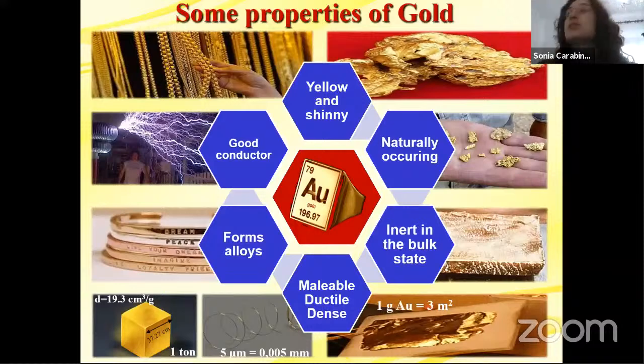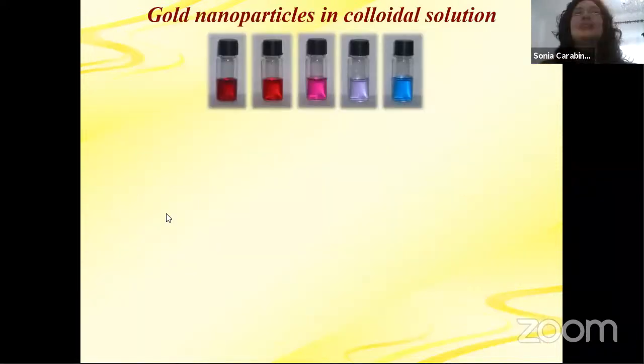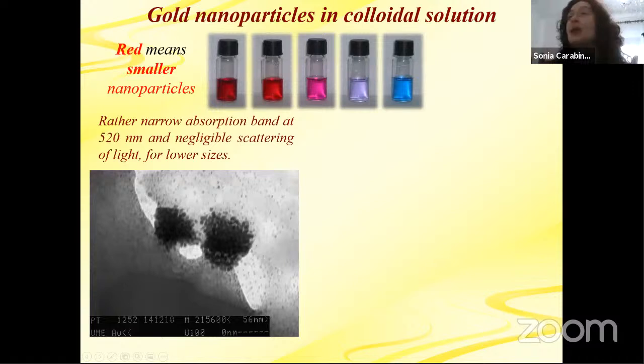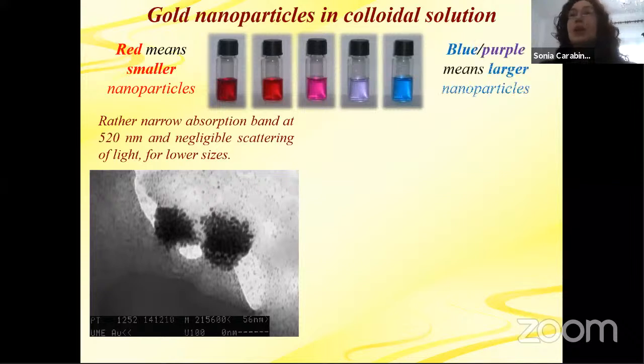Well, we have gold nanoparticles in solution. They have different colors. They are not yellow like the gold in the bulk state. So it's quite interesting, because if we have a red solution, it means we have smaller nanoparticles. They have a narrow absorption band at 520 nanometers and negligible scattering of light for lower sizes. But if we have blue or purple solutions, then we have larger nanoparticles, and the absorption band shifts to longer wavelengths, and light scattering becomes marked for these larger sizes.